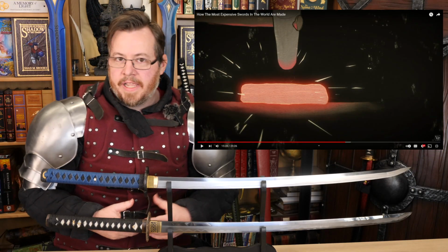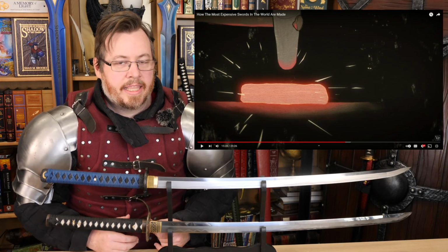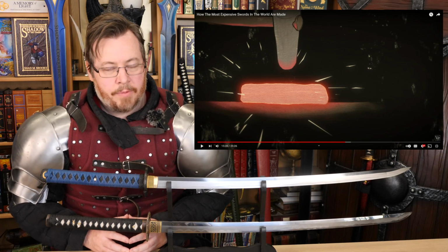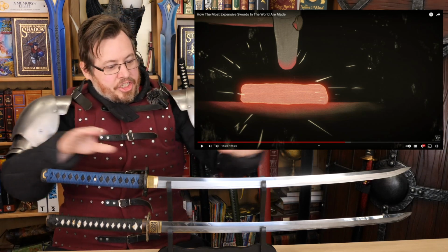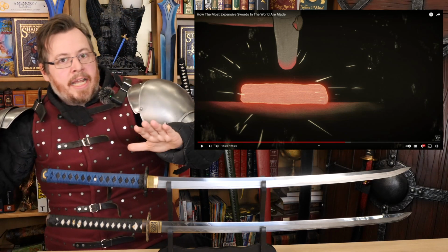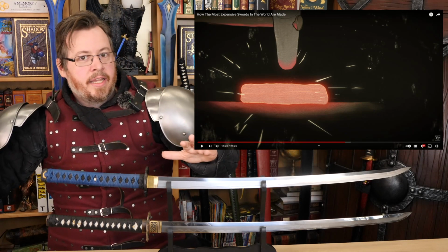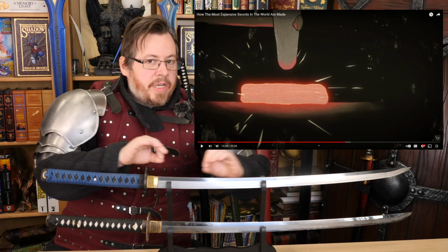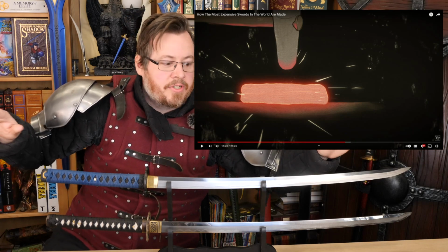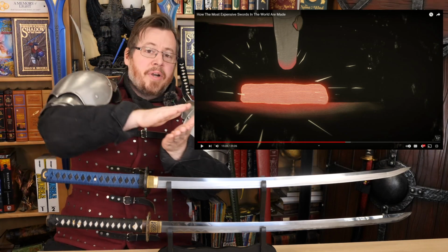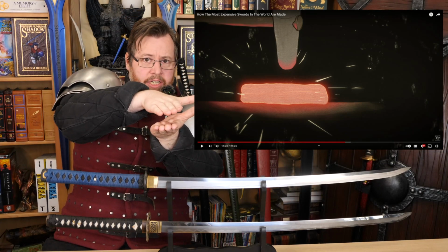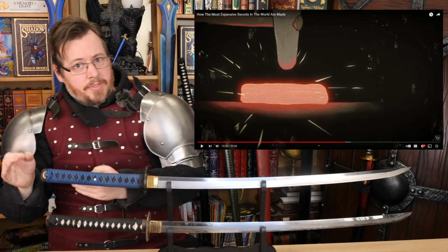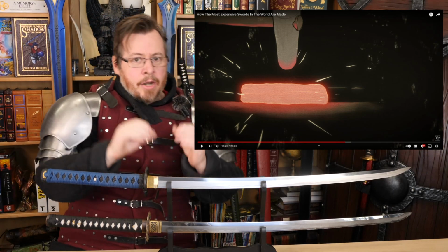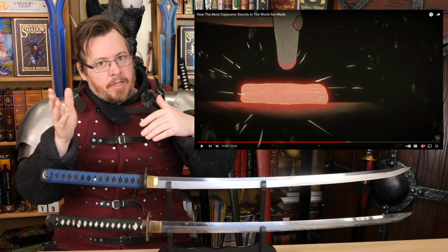And so there is a phase in the smithing process that they call normalizing, where they will heat up the shape of the blade, right, and let it cool down naturally, then heat it up and cool it down naturally, and they're normalizing the steel to reset the grain structure, because sometimes the grain structure that gets put into steel when you're hammering it down, like you're compressing those grain structures, can be detrimental. And it's far better, and also can cause warps on the quench.